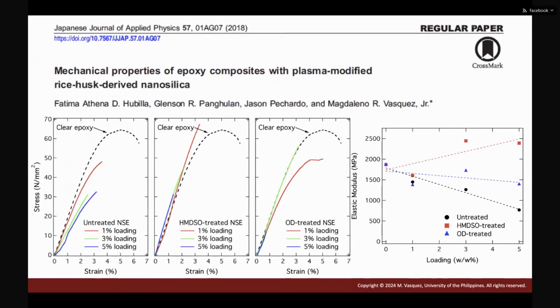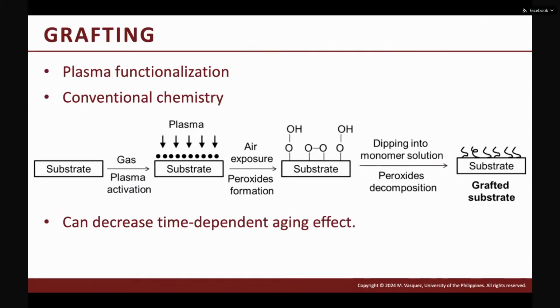So here's an example. This is a rice husk. Rice husk is just a waste, and we want to extract nanosilica from rice husk. In order for us to use the nanosilica, we treat it with plasma. So we're able to functionalize the nanosilica with mostly silane groups and improve its compatibility with epoxy. So we use modified nanosilica in epoxy resin.